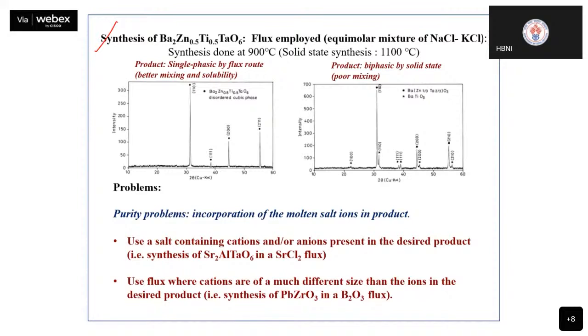Okay, so this is the same compound I tried to prepare by solid state route, and because solid state does not allow for good homogeneity, despite a multi-step process, I got two phases. This was carried out by salt flux, and this was done at 1100, this at 900. Single phasic product, lower temperature.